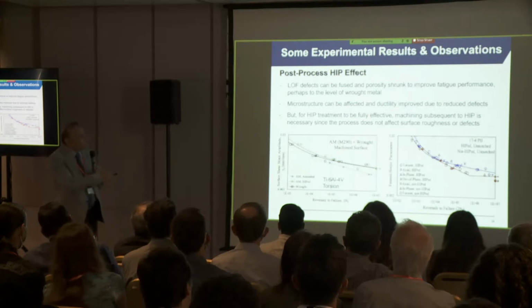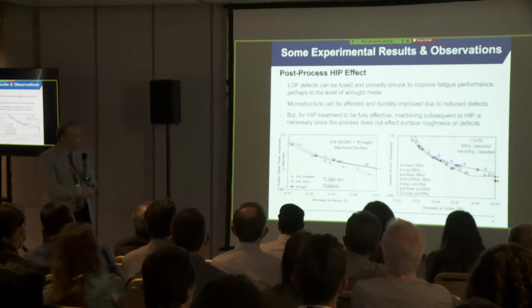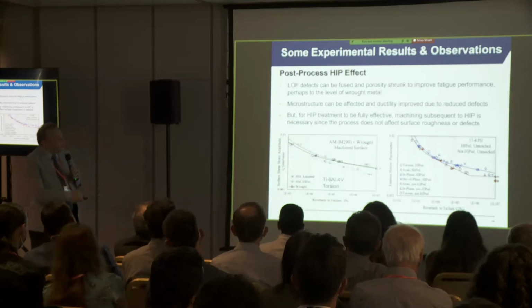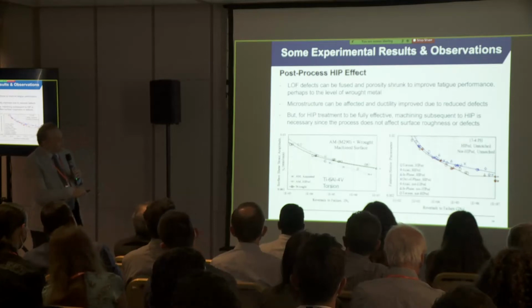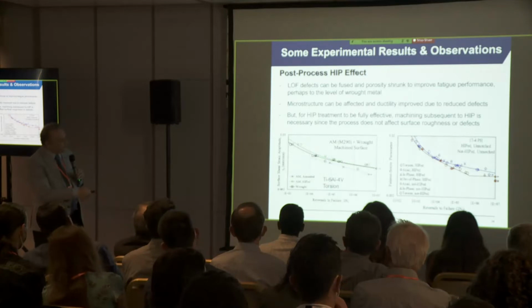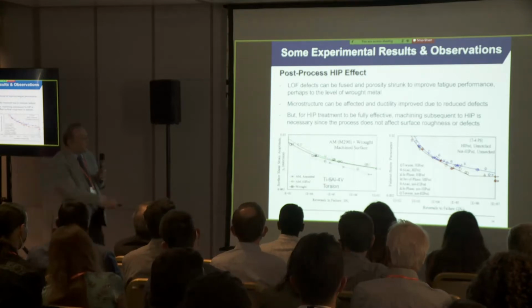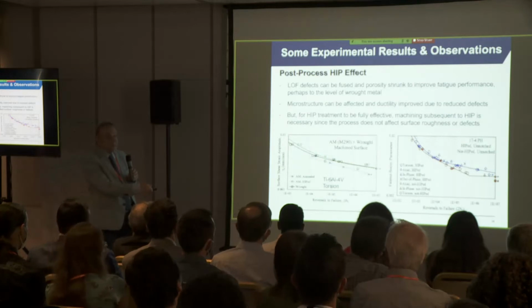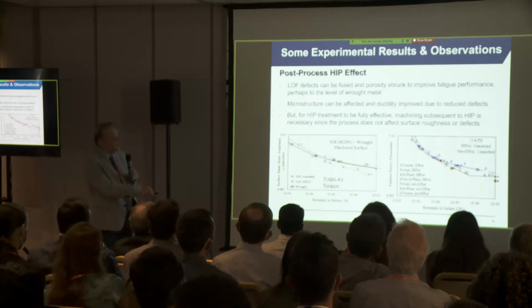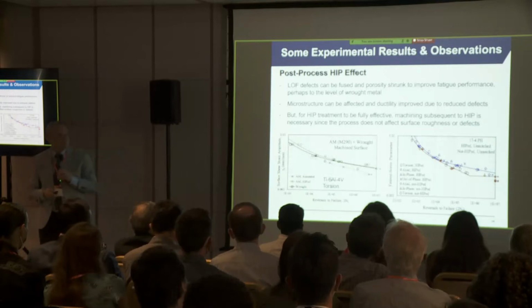Post-processing, such as HIPping, has a big effect. Again, without HIPping, you may have a performance like this, but with HIPping, you get the green data, which is very close to the rod data. And similarly for 17-4 stainless steel, the red data are all without HIP, the blue data are all with HIPping.